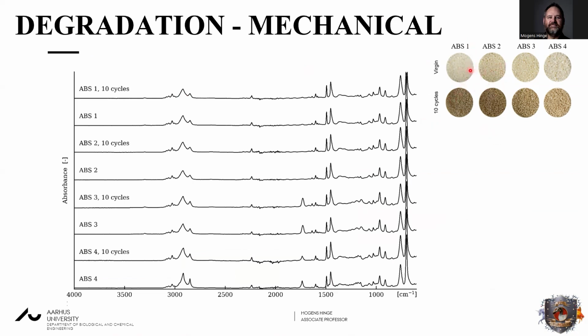Now, when we start to look at it chemically by the IR, the first thing we see is that we compare here the 10 cycles and then the no cycle or 1 cycle, because it's produced in the same way. So the 10 cycle and 1 cycle, if you compare those, then here on the styrene, we don't see a lot of change. We don't see it here. We don't see it here. So basically, we can safely conclude that the styrene phase seems to be withstanding at least the mechanical degradation. Again, if you take number 2, then these pairs are also not changed. These are not changed. So in that way, the spectra are the same, and thus we don't see any change.